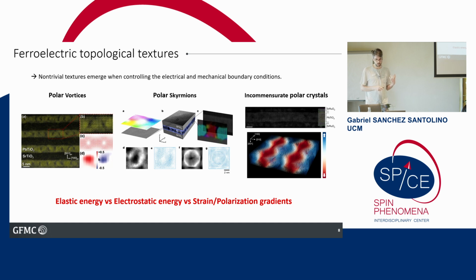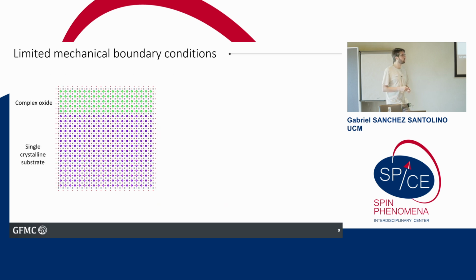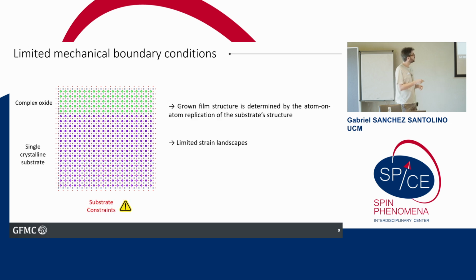But all these systems are still constrained due to the epitaxial growth of the ferroelectric layers. So usually when we do complex oxides and ferroelectrics, we have a single crystalline substrate, and we grow our atoms on top with pulsed laser deposition or sputtering or whatever, and we have this atom by atom replication of the structure. So the mechanical boundary conditions that we can apply at the interface are basically limited by the lattice parameter of the substrate, so we can do either compressive strain or tensile strain. So the strain landscapes that we can create are very limited.